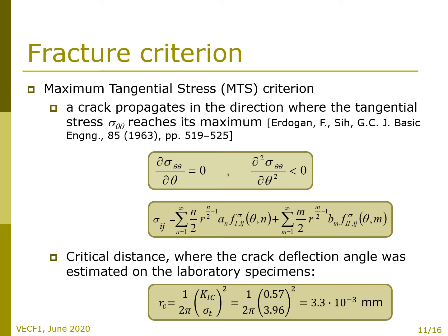Note that whereas the classical MTS criterion is independent of any other parameter, its multi-parameter form depends on the radial distance where it is used. This distance is often called the critical distance, and several recommendations on its estimation can be found in literature. For purposes of this research, the relation derived by Sih was applied.